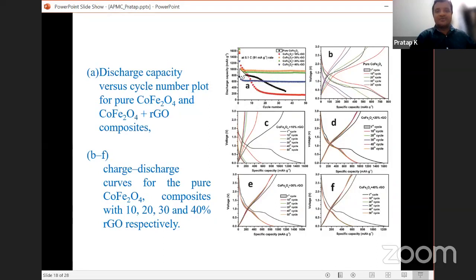So the orange one, cobalt ferrite with 20% RGO, this one here. It is showing a capacity of 1000, and even after 50 cycles it is stable, which means it is not leaking. It is regaining its own capacity, and it is really good. That is why we are using this cobalt ferrite with 20% RGO.